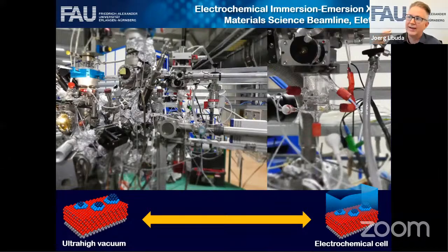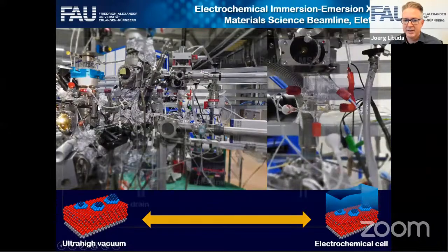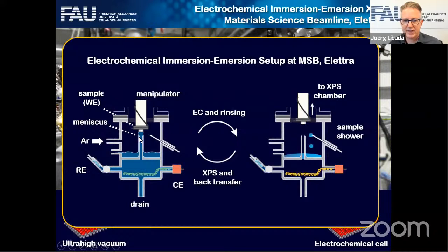If you want to do conventional electrochemical experiments, the only way is to couple really ex situ via a transfer system. So typically what people do is they use the electrochemical cell. This is something we set up at the synchrotron ELETTRA: an electrochemical cell attached to the vacuum system. How does it work? You have the electrochemical cell, you bring your single crystal in contact with the electrolyte to do the electrochemistry. And then what we use is what we call a sample shower to wash the sample, and then the sample is brought back to the vacuum environment.